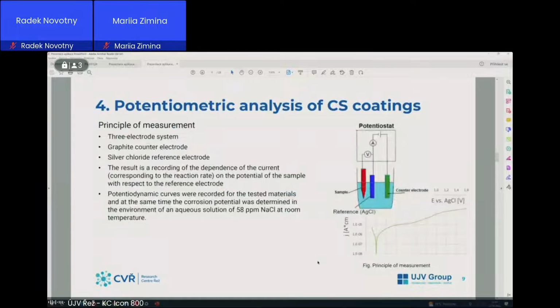Other tests which were performed are potentiometric analysis of cold spray coating. A principle of measurement you can see on this figure. We are using 3 electrode system: graphite counter electrode, silver chloride reference electrode. The result is recording of the dependence of the current on the potential of the sample with respect to the reference electrode. Potentiodynamic curves were recorded for the tested materials, and at the same time the corrosion potential was determined in the environment of an aqueous solution of 58 ppm sodium chloride at room temperature.